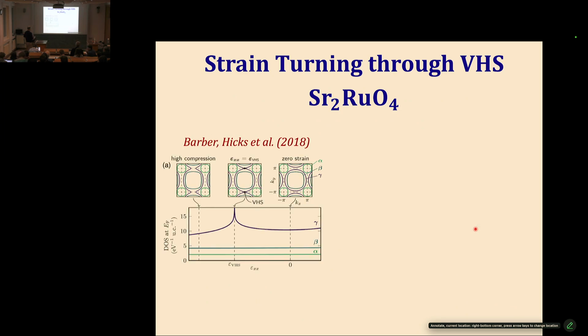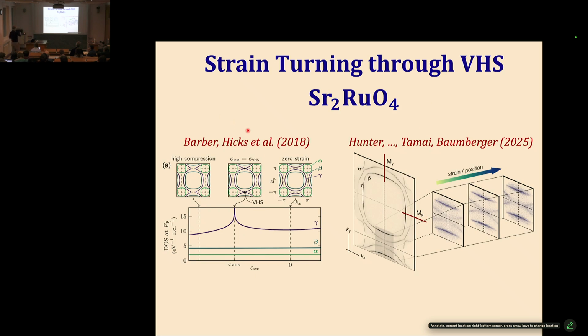And this was first demonstrated by Clifford Hicks et al. So this is a DFT calculation. He did an experiment that was shown by Michael, that I'll show in the next slide. But nowadays you can really image this using ARPES. So Felix and Anna's group do an ARPES experiment on a strained sample, and different parts of the sample have a different strain. So by imaging the band structure as a function of position, you can really see this topological transition occurring. And this is occurring as a function of strain.